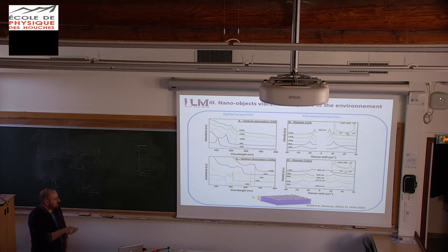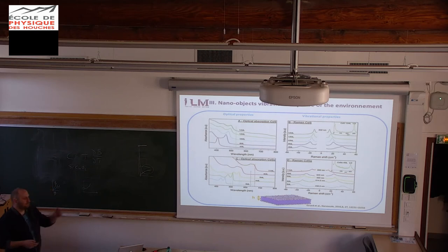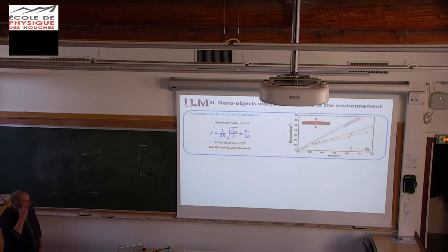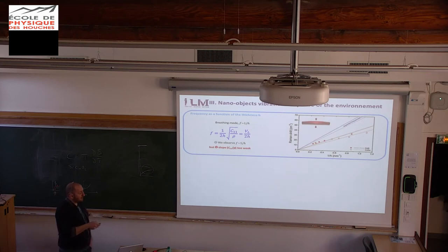And you see there is a dependency of the vibration mode frequency as a function of the thickness. So the thicker nanoparticles have a lower frequency, as expected. So it was fine. We were able to deduce the thickness of their nanoplatelets. They were quite happy with that. But in reality, we are not able to, because if we compare to the Lamb model for this type of shape, you see that our data are quite far from the expected frequencies.